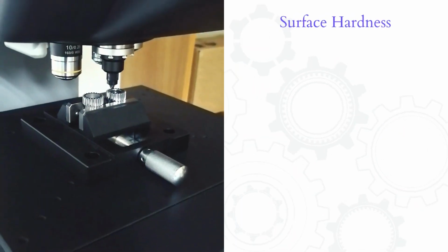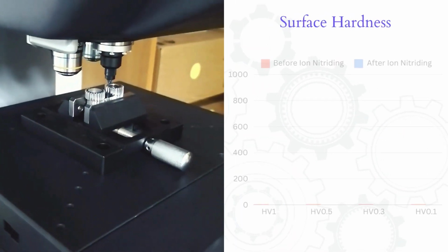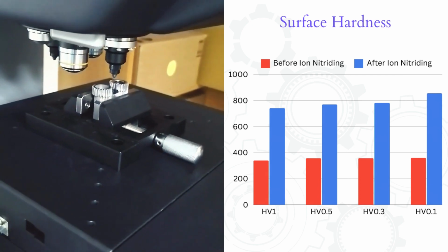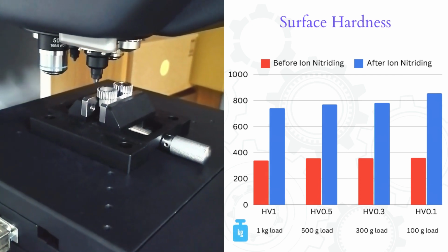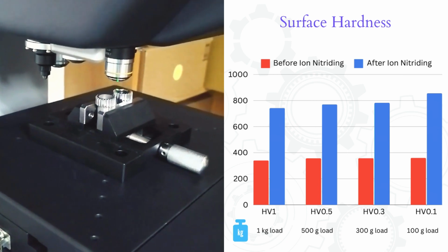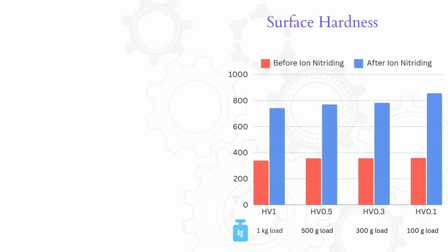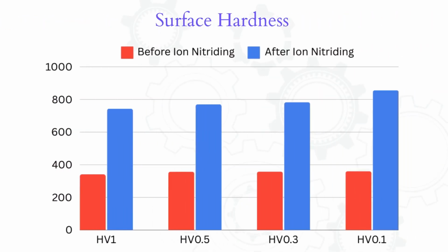We will measure the surface hardness again. The surface hardness with a higher load is a bit lower compared to the measurement with lower loads. This is because measuring with a higher load penetrates deeper into the layer and is reaching a place with less diffused nitrogen atoms. While the smallest load of 100 grams will most probably show us the most accurate surface hardness, because it will penetrate less of the surface and will have a higher percentage of diffused nitrogen. In most cases, it will even penetrate only in the achieved white layer.